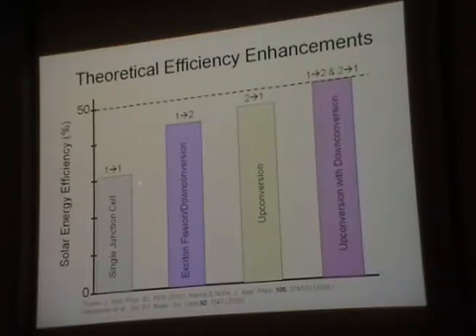And the maximum you're going to get is about 42 or 43%, depending on some details in the calculation. So you can go from 32% to 43%. Turns out up conversion, where you get the low energy photons and just make them into high energy photons, is even better. You can get up to 46 or 47%. If you combine them, you hit the 50% mark, 49, 50% total efficiency for a single junction cell.